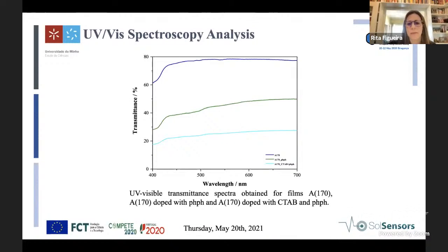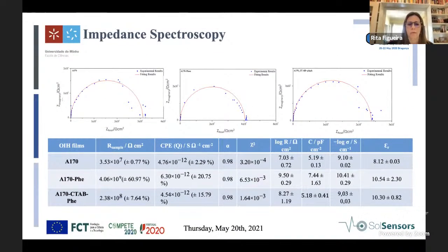From the spectroscopy analysis, we see that the presence of CTAB gave us a decrease in the transmittance, indicated by these values here. And when we use phenolphthalein, we have a decrease compared to samples without phenolphthalein. So in the data obtained for the films, you can see there's a difference in the resistance with and without phenolphthalein, and CTAB also influences the resistance of the samples.